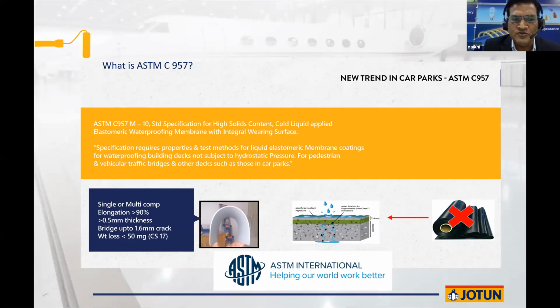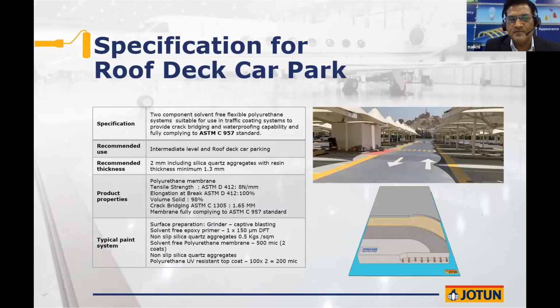minimum, the weight loss in the abrasion property should be less than 50 milligrams. That means every 1,000 cycles, the wearing of the coating should not exceed 50 milligrams. So you can see here, the specification clearly states that it has to comply with the ASTM C957 standard.